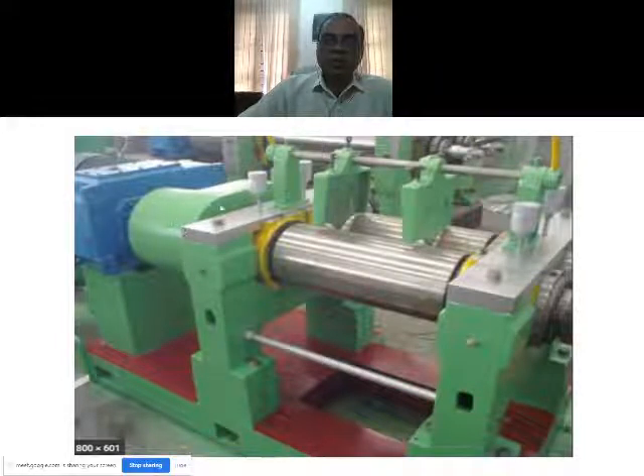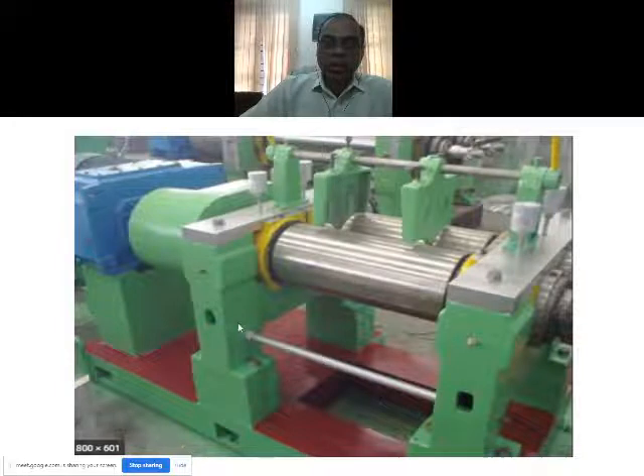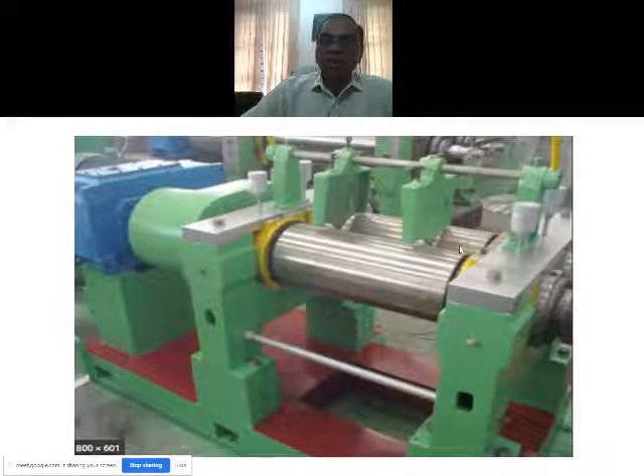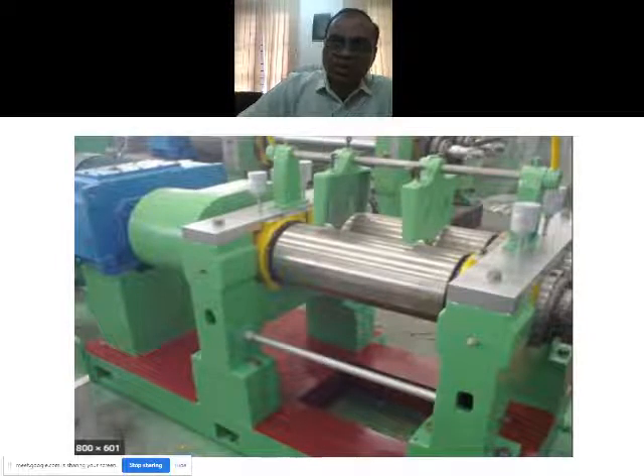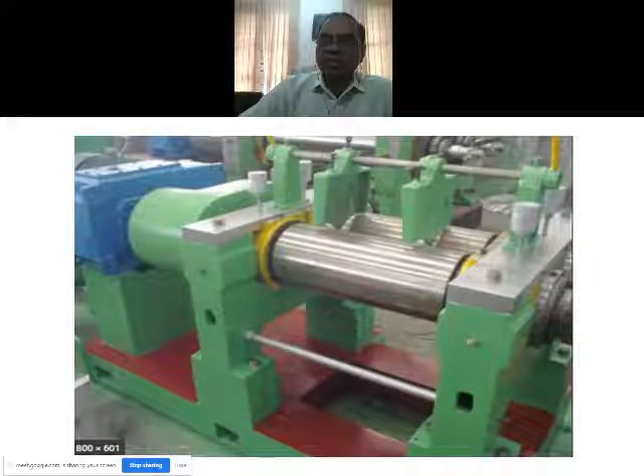So in this case, this section represents the gear, and this is the drive system: the motor, the reduction gear, and the gear which connects the front and back rolls. With a reduction gear, the RPM of the motor is cut down to a smaller value, and then this is connected through the gear to the back roll, and these two are rotated through this gear system. You can see one bolt here, one bolt here, with a handle which you can rotate to move the rolls back and forth so that the nip can be adjusted wherever you want. Normally you keep it between almost 0 to 6 mm, or 2 mm as the case may be. Normally it's kept at less than 2 mm. It depends on volume and on the shear rate that is required.